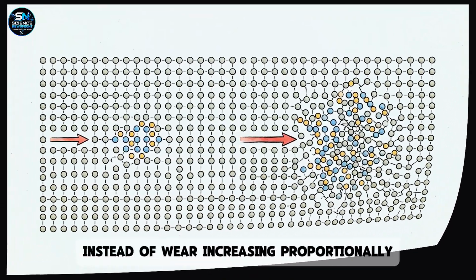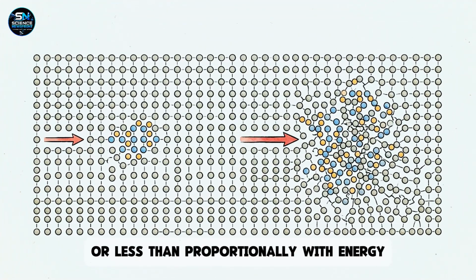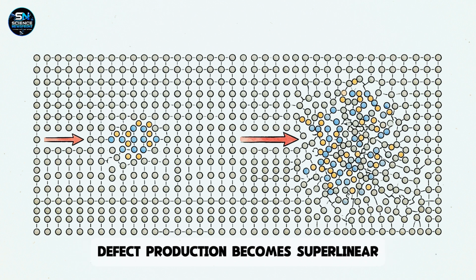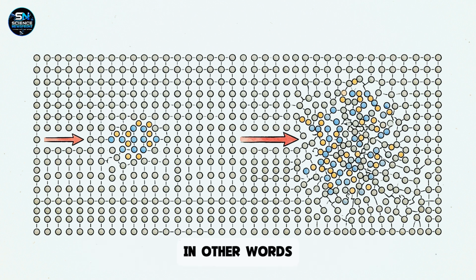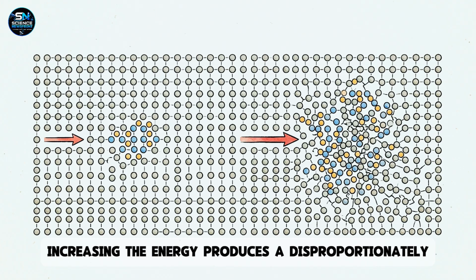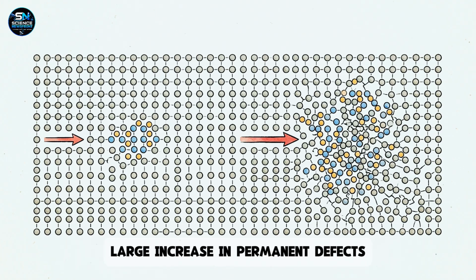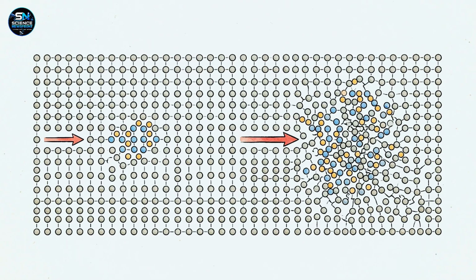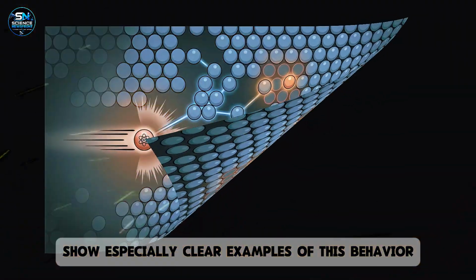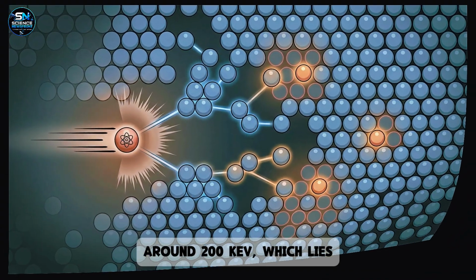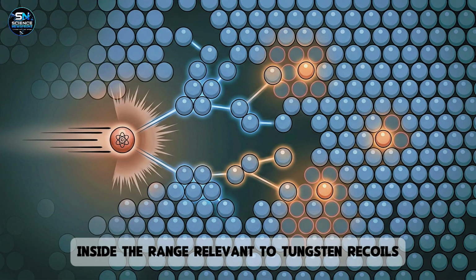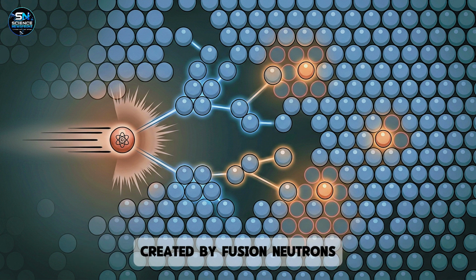Instead of wear increasing proportionally, or less than proportionally with energy, defect production becomes superlinear. In other words, increasing the energy produces a disproportionately large increase in permanent defects. The simulations show especially clear examples of this behavior around 200 keV, which lies inside the range relevant to tungsten recoils created by fusion neutrons. This is why the result matters for fusion material modeling.